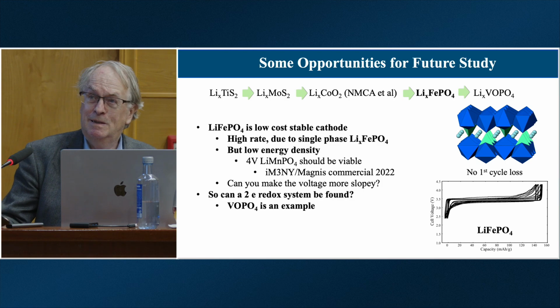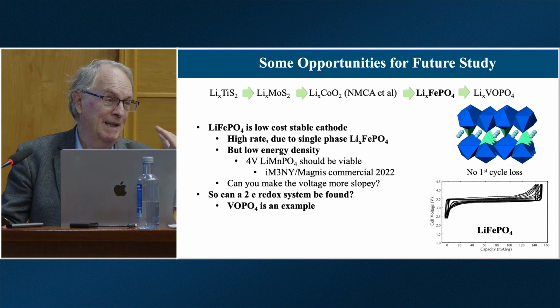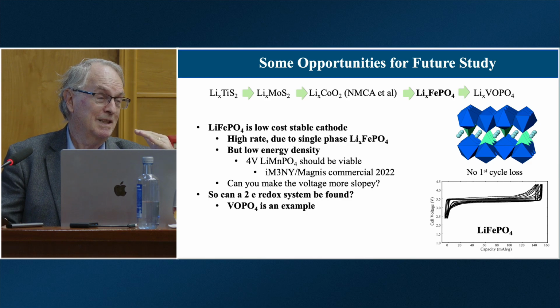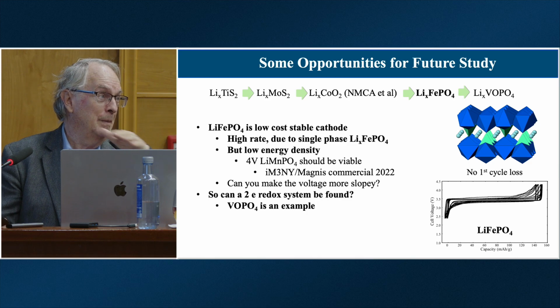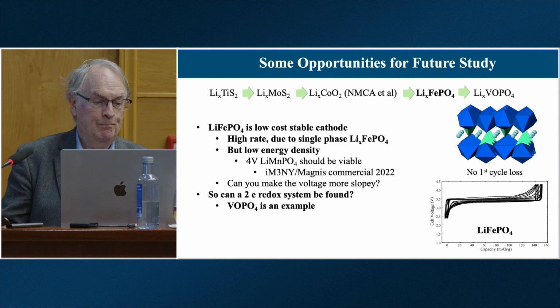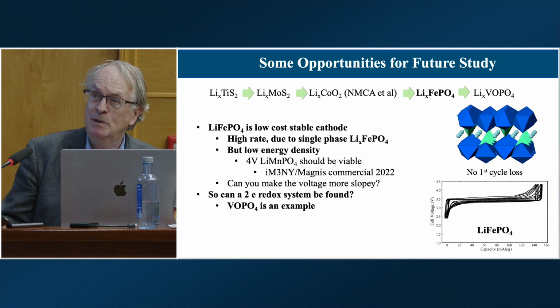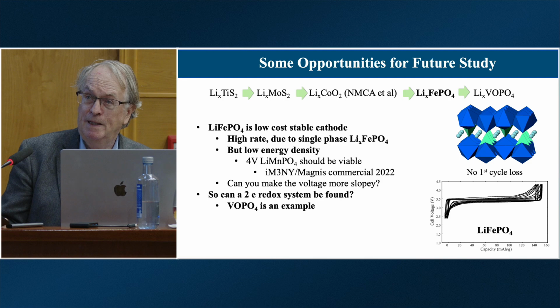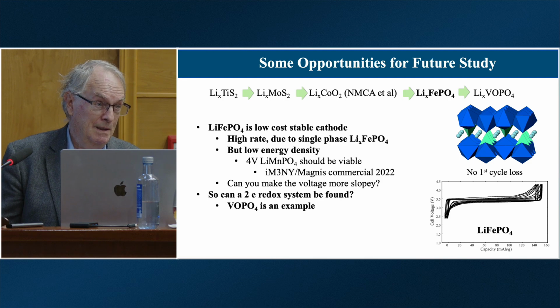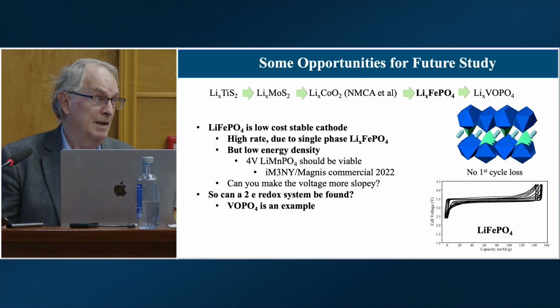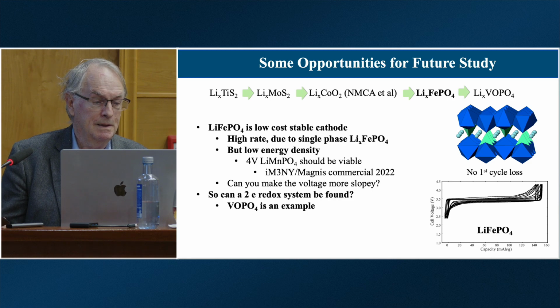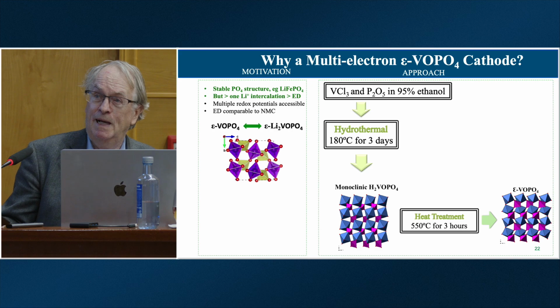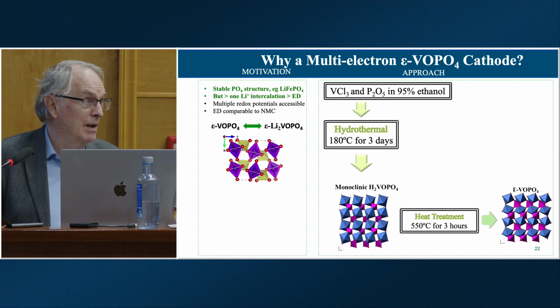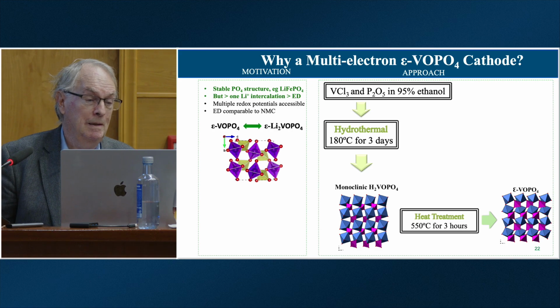So one of the things we're trying to do in the lab is, can we make that discharge curve slightly slopey, even if it's only 300 millivolts, so you know where you are. But our real goal is to modify this material, look at other phosphates, and see if we can't get the energy density up. And we've been working, let's say, using vanadium. And vanadium, again, is a nice three-dimensional lattice, so it's very stable chemically.